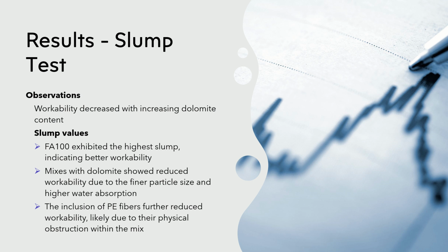So the results of the slump test revealed that fluidity and workability of the concrete mix were reduced when we added dolomite and GGBS to geopolymer concrete. The mix became less workable and didn't flow easily. This is because dolomite absorbs more water and has finer particles. Adding polyethylene fiber also made the mix stiffer, further reducing its fluidity. Overall, mixes with more dolomite and fiber had lower slump values, meaning they were less easy to work with.